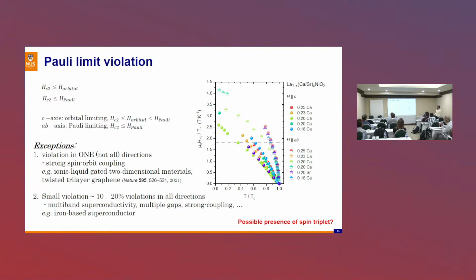If we compare to the heavy fermion systems, for example, this is the only case where we can see a violation in all directions, which is significant. And this is, of course, a triplet superconductor, P wave. So whether this is something to do with that is probably very difficult to say. You really need to do other experiments to confirm the reasons for these violations.